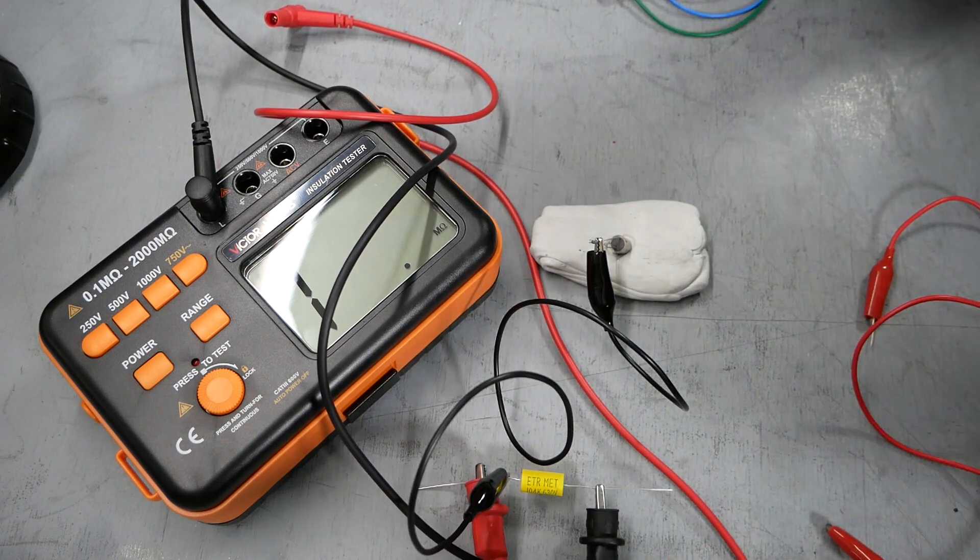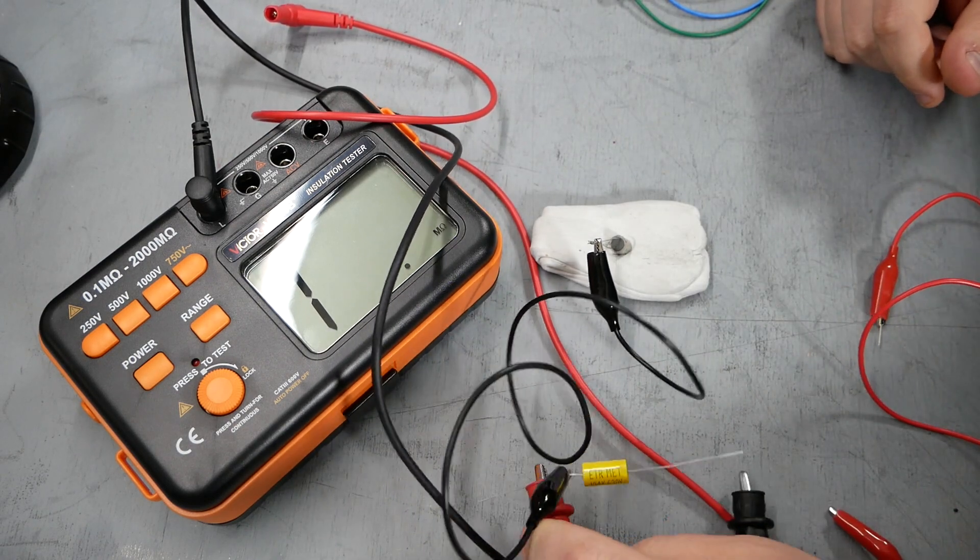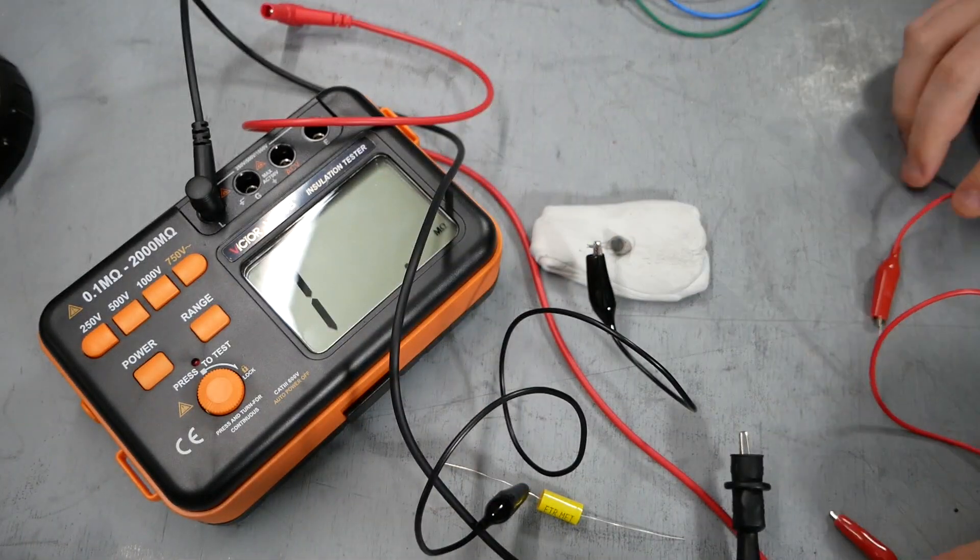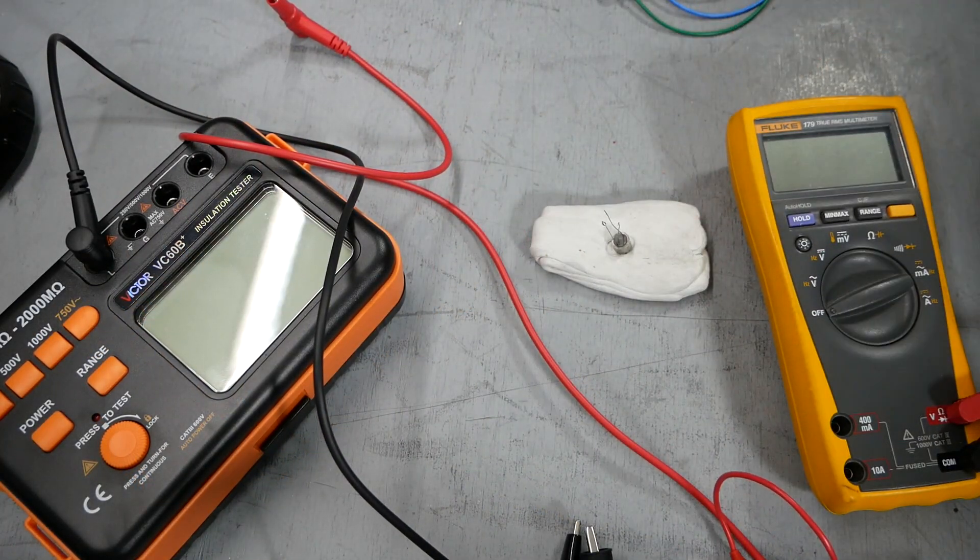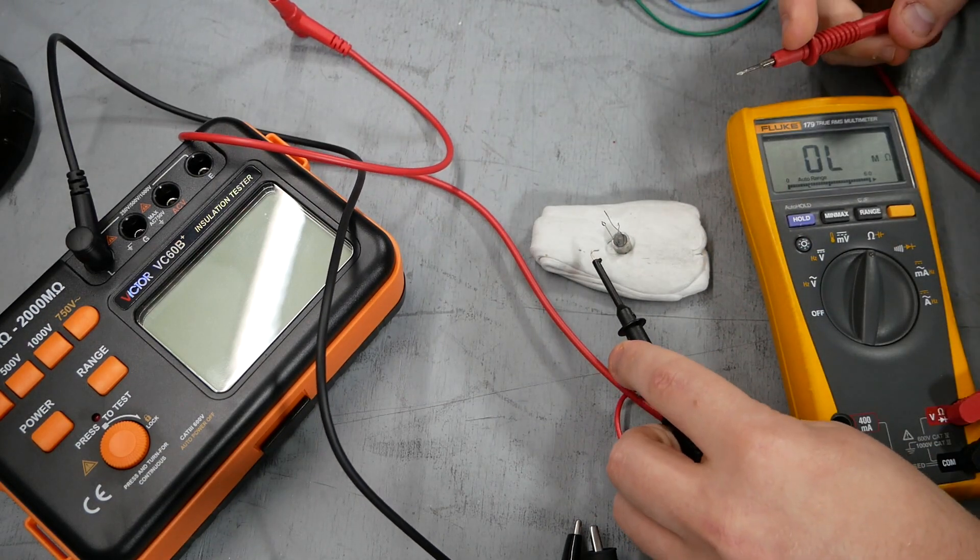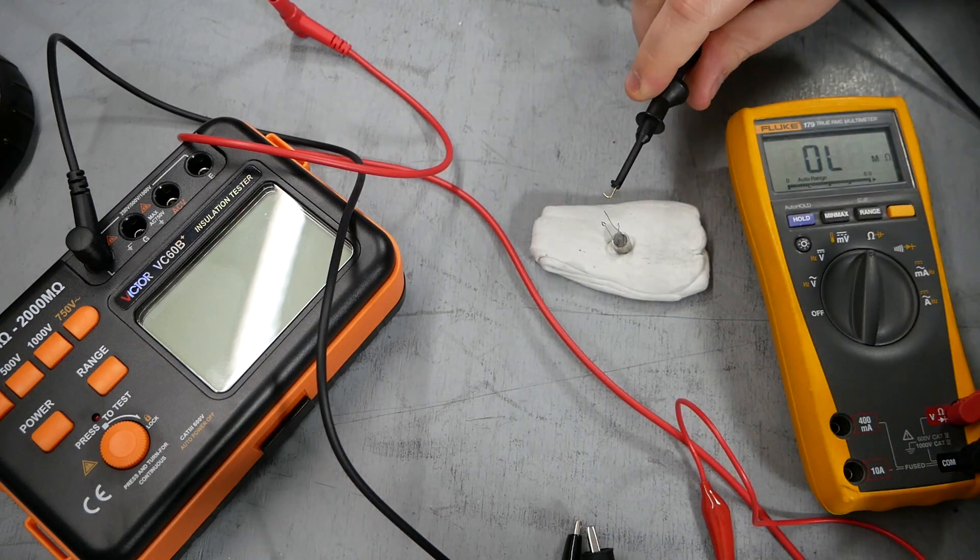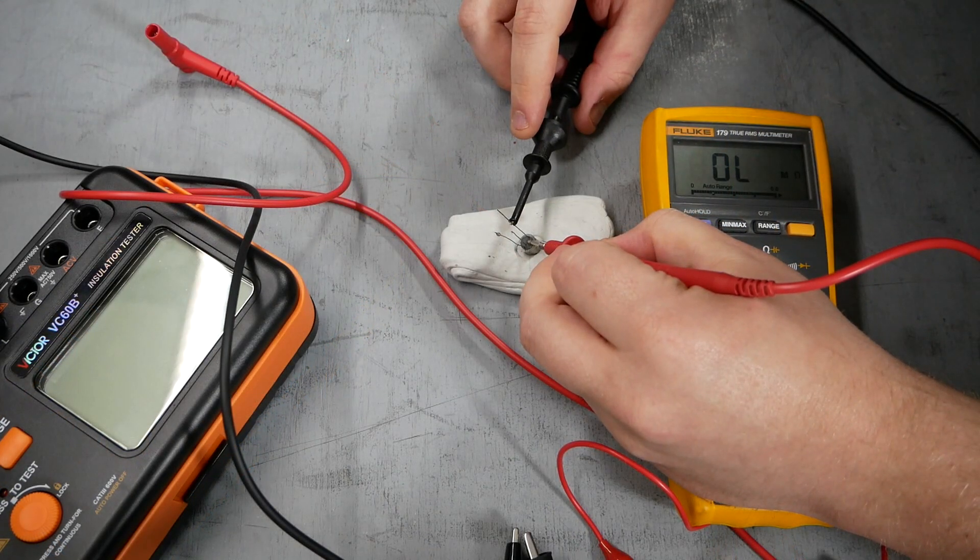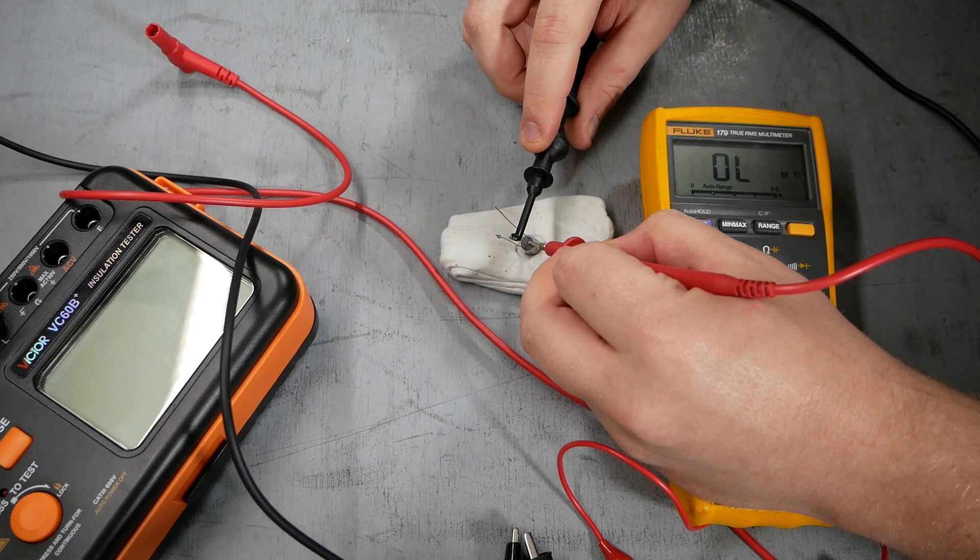Okay, so that definitely sparked. So that means there was something happened. You know, if that shield wasn't either connecting to the electrodes or wasn't at least very close, then nothing should have happened. So let's see if we cleared up that whisker. Or maybe we blew up the whole transistor. Who knows? Let's find out. I believe it was on the collector. We had that 18 ohm path. Okay, looks like that whisker is gone.